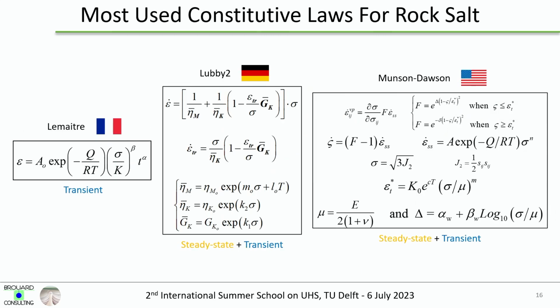When we look at, let's say, macroscopic laws for modeling salt caverns, there are, in the world, 3 main types of laws that are considered. It depends on where the creep tests were performed in the lab. For instance, if you ask the School of Mines in France to perform creep tests, they will provide you with a set of parameters for the so-called Lemaitre law. So it's a very simple law here on the left. If it's in Germany, you will have the Lubby law, and in the US, it will be the Munson-Dawson law.